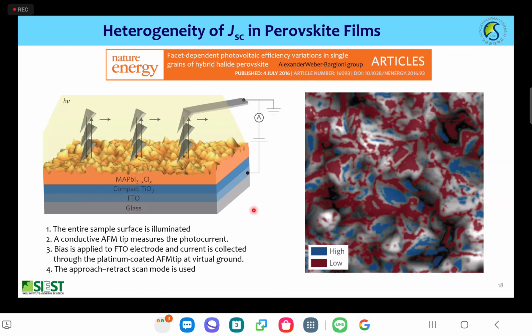According to a previous report, the perovskite surface does not give us homogeneous photocurrent. When you measure the photocurrent by AFM, you can find from the conventional perovskite solar cell film that there is some high photocurrent density, and there is low photocurrent. This motivated us to develop a facet dependent photocurrent density.